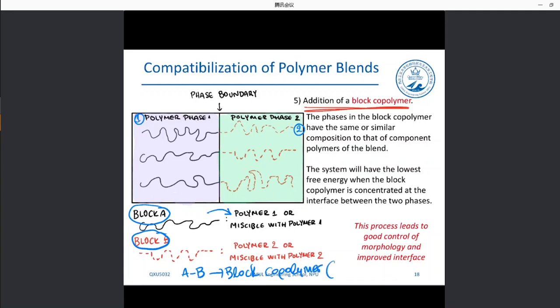Usually we write the block copolymers like that, A_n B_m, or something like that. And block B is, let's say, miscible with polymer 2, or friendly with polymer 2. Then we induce compatibilization of the polymer blend, because this system has its lower free energy when the block copolymer is concentrated at the interface. So block A does not pass to phase 2; it stays in phase 1, while block B stays in phase 2. That leads to the lowest free energy.